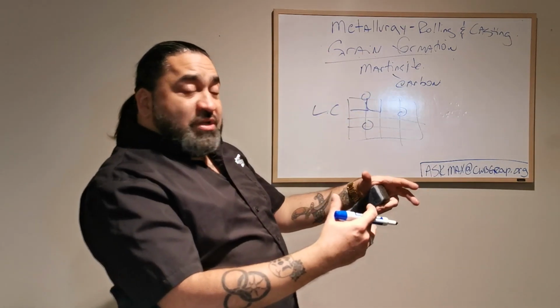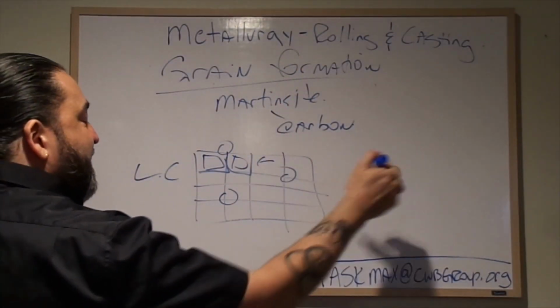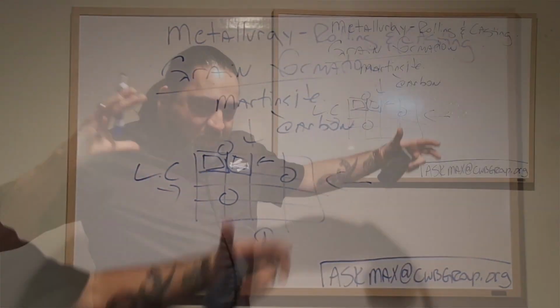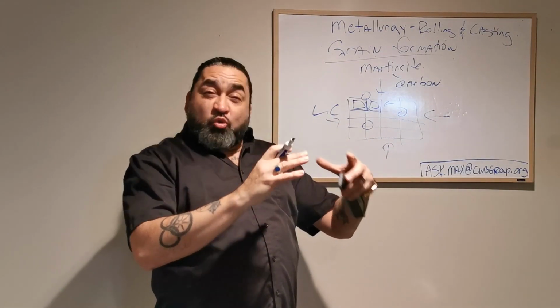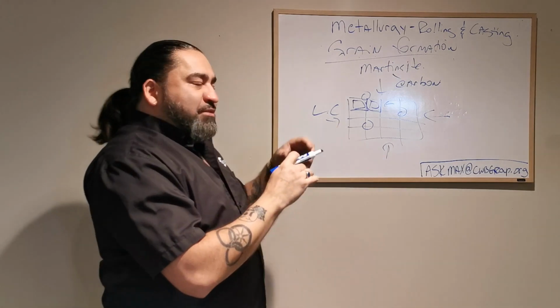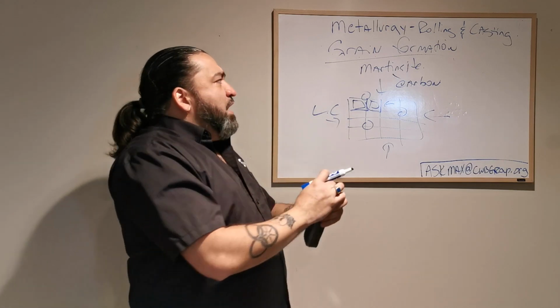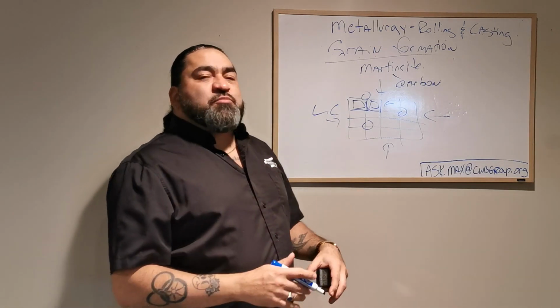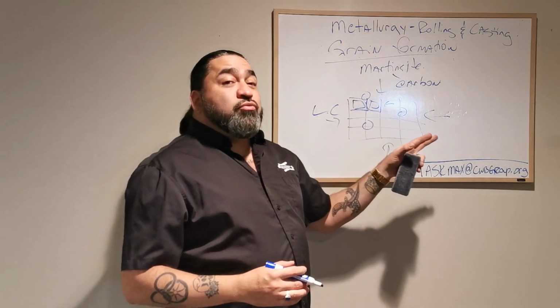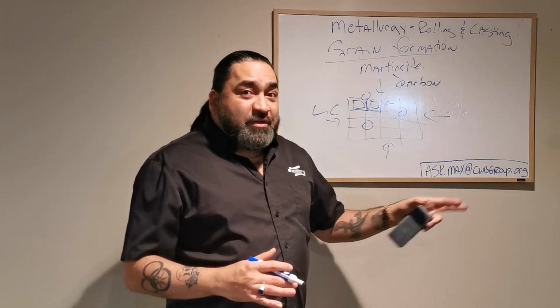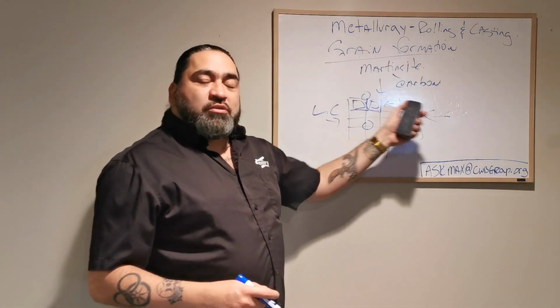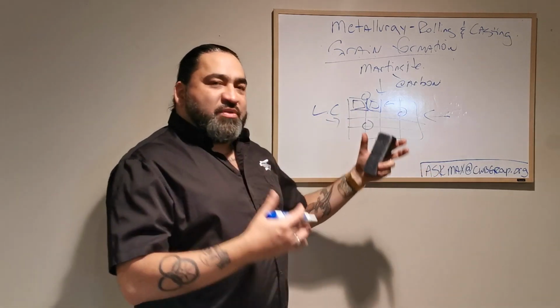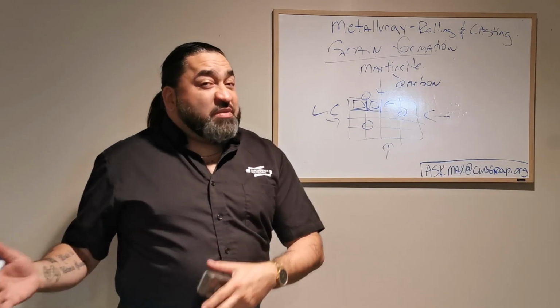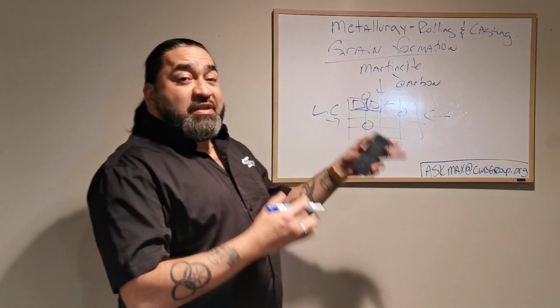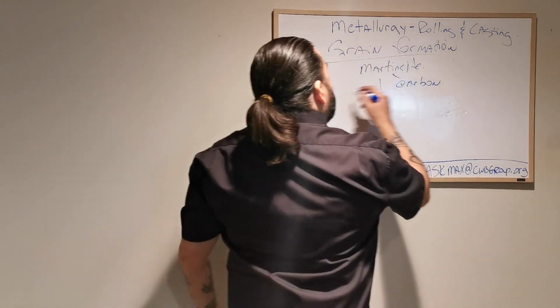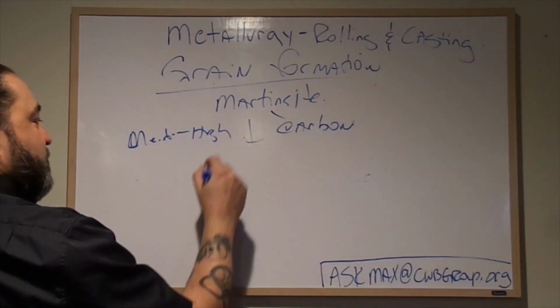Now, if you quench this, what happens is that it will all squeeze in. You have quenched it, caused those seeds to come back quicker and tighter, and you've decreased the grain size, made smaller, tighter grains, increased the volume of grain boundaries within the material, which makes it much harder. But have you changed the carbon? No, you haven't. So can I get martensite from quenching low carbon steel? No, because nothing happened. The carbon is still in there. Yes, the material got harder, but that's because you quenched it and changed the grain growth, not because of any carbon. Martensite will only occur in medium to high carbon steels.